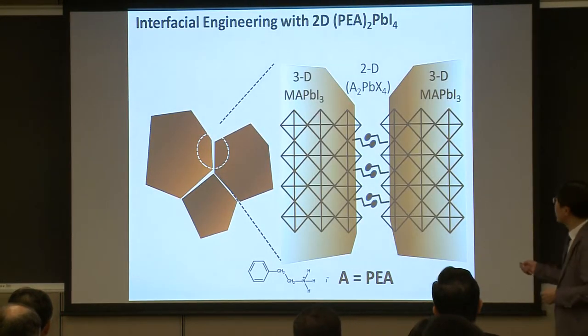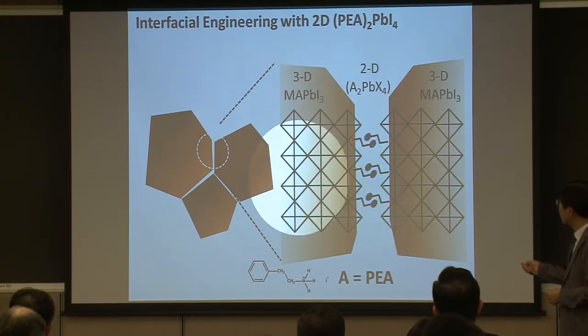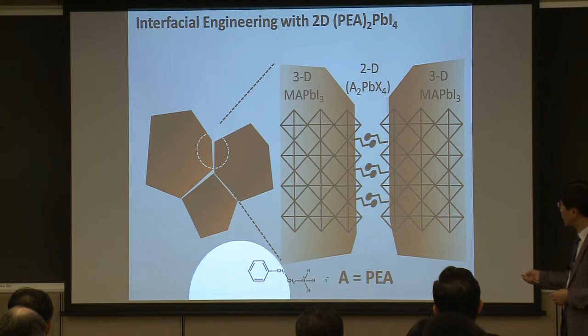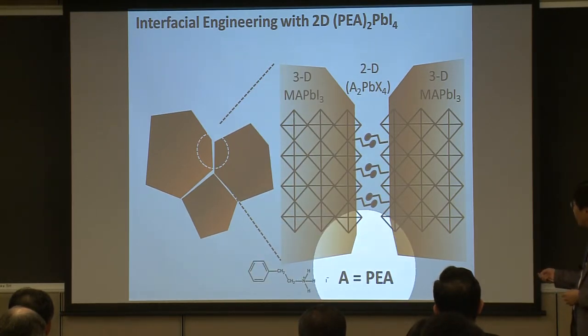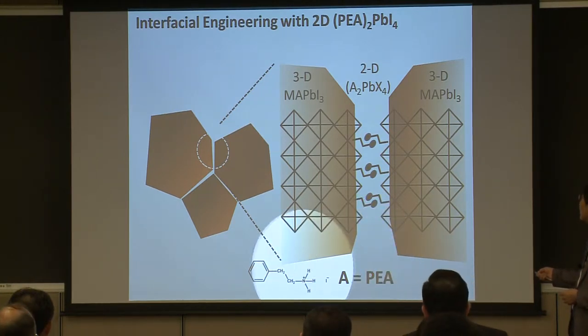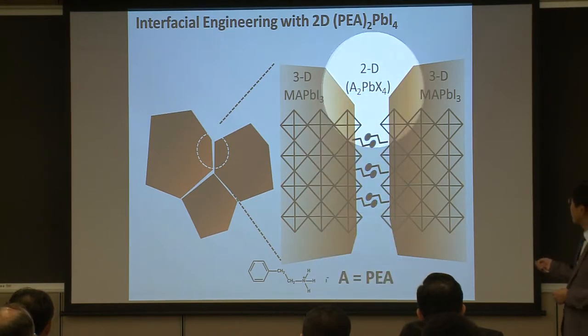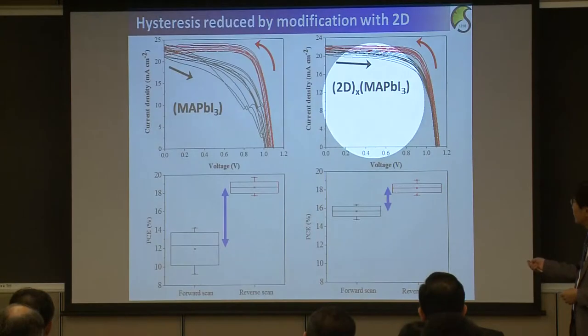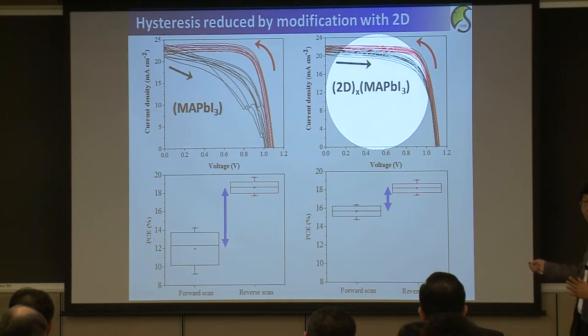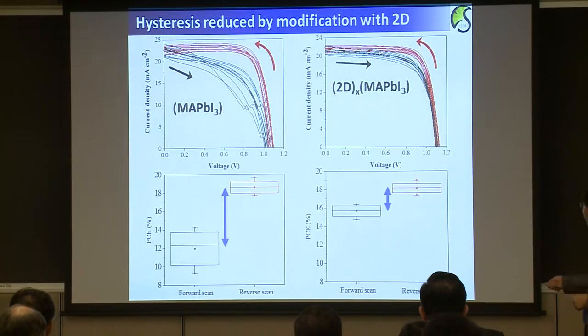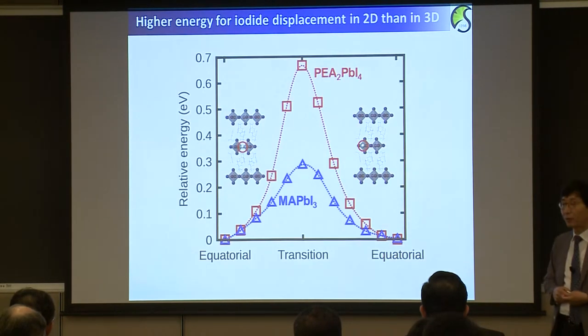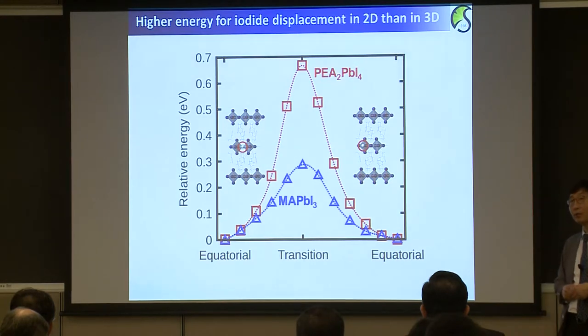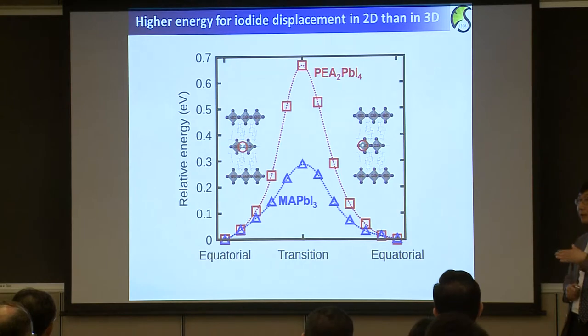First, we introduced the two-dimensional perovskite in between the three-dimensional perovskite. And then we used the phenylethyl ammonium cation. After introduction of two-dimensional perovskite in between three-dimensional perovskite, we found a great reduction of the IV hysteresis here. And probably one of the reasons for hysteresis is related to the ion migration due to defects of the iodide. So ion migration can accumulate charges at the interface.